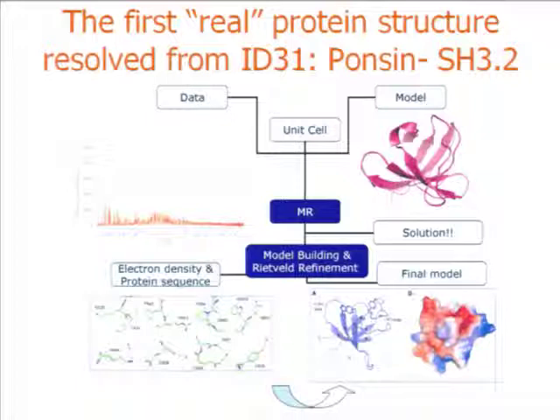Now, this was a quite good result, but then we had to rebuild 40% of the protein chain with the right amino acids, and this could not be automated because the density maps are noisy and are biased. So we could use various different types of maps in order to determine the positions of the 40% of the amino acids which were not correct. And this procedure took a few months to complete. Finally, by using multiple profiles corresponding to slightly different lattice parameters induced either by radiation damage or by slightly different crystallization conditions, we refined the structure and we got a model which looks like this.